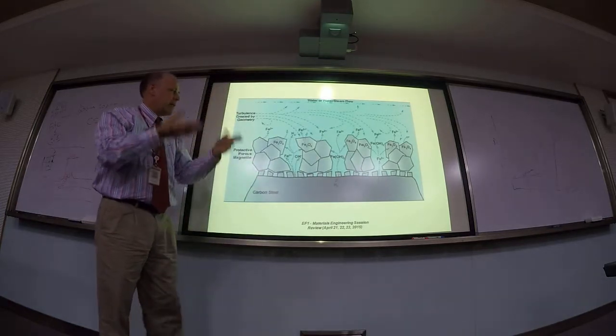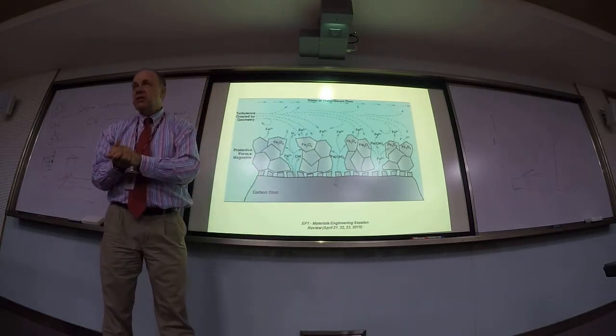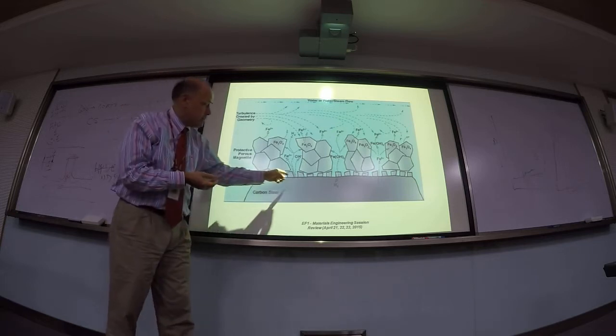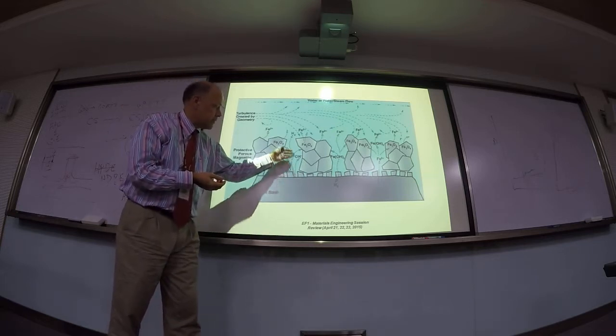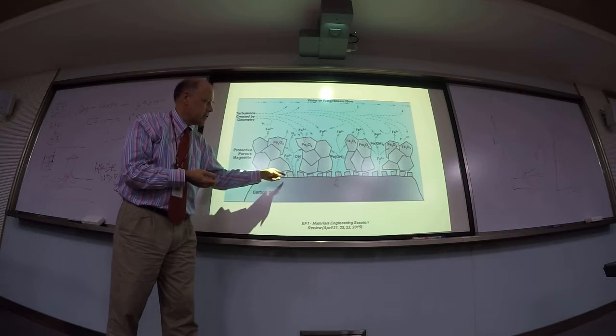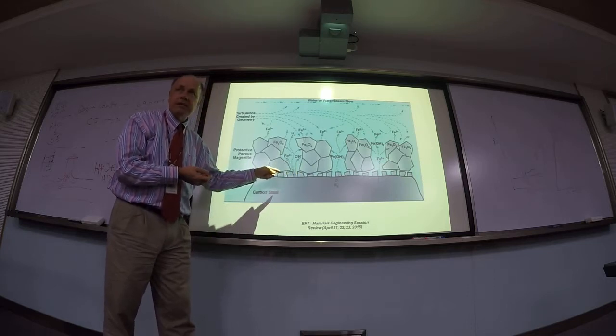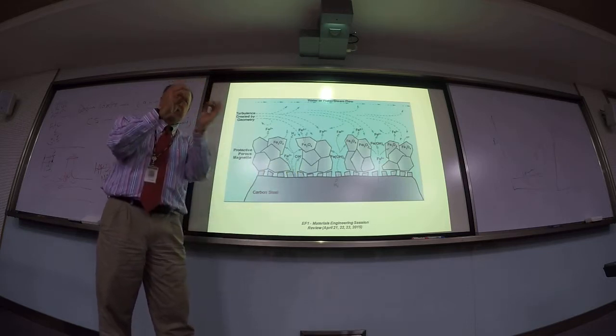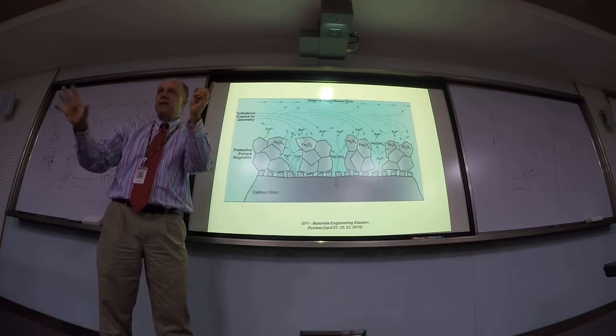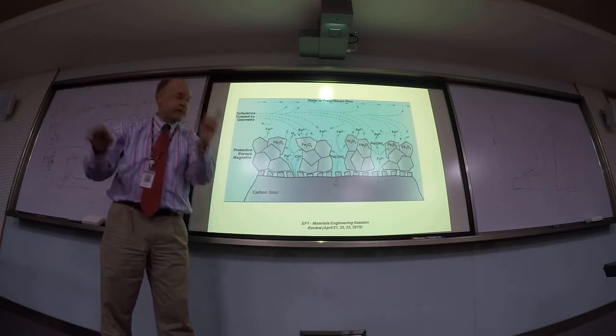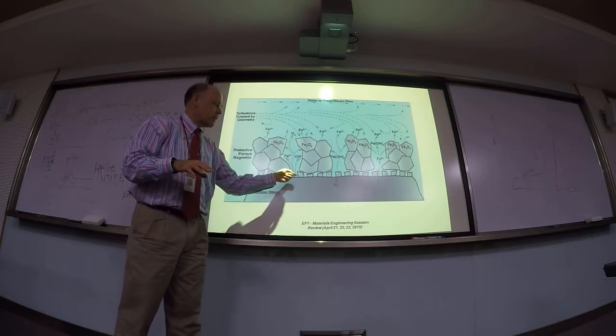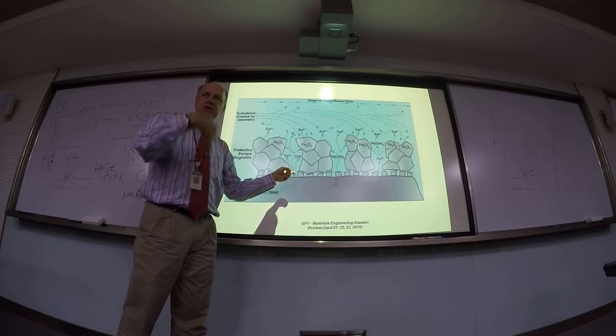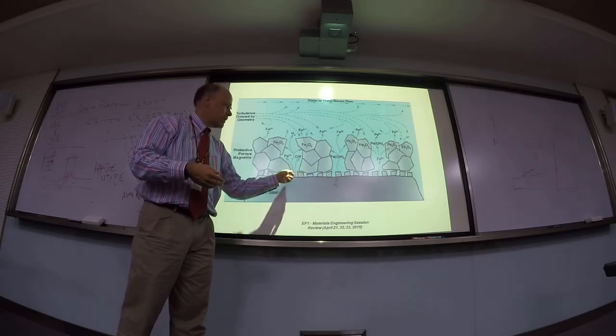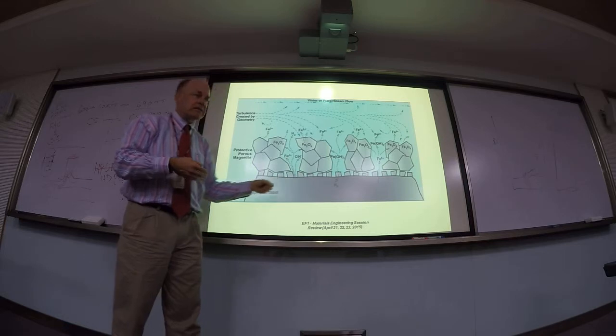So maybe, I don't know the material science of fact, but maybe if we have chrome here, the iron disappears, but the chrome stays, and then the chrome forms a protective layer down here. That's my theory. 0.2 is only 1 out of every 500 iron. But if we remove 500 iron and the chrome is still there, and then it's more chrome and more chrome, eventually we get a chrome layer here that forms protection. Okay?